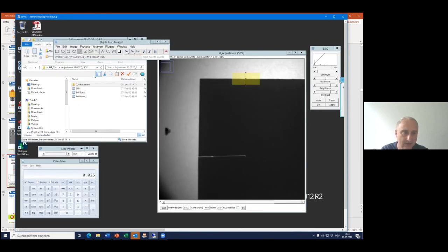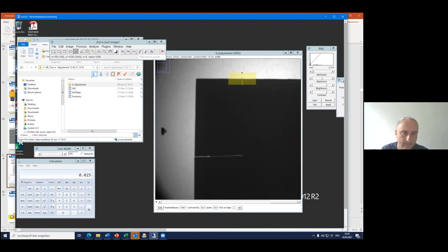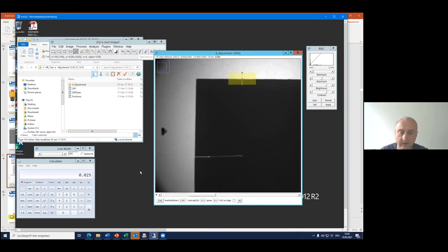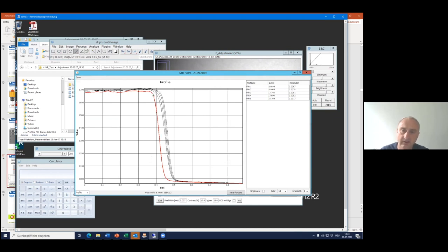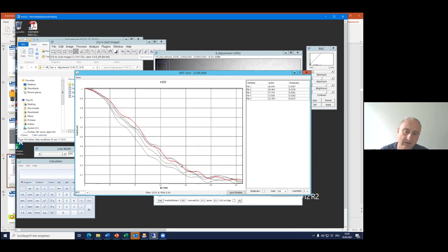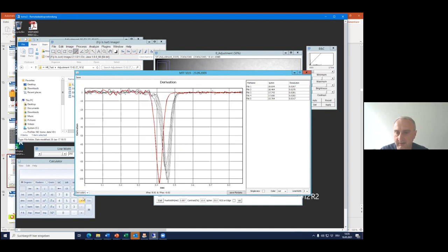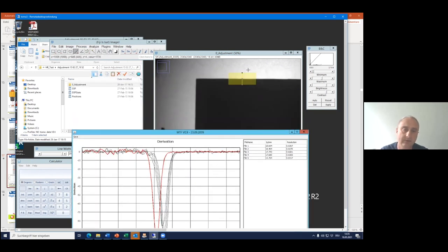Here I should define again the pixel size and the parameters. So we have again the 7 micrometer, and the expected line pairs per millimeter is about 25. So here you see that we have a much smoother profile. The calculation of the resolution is improved, and the obtained MTF is much more reliable. So this means that if you are going to really estimate the resolution, it is good to take more points for the statistics and also to have a good orientation of your line profile.